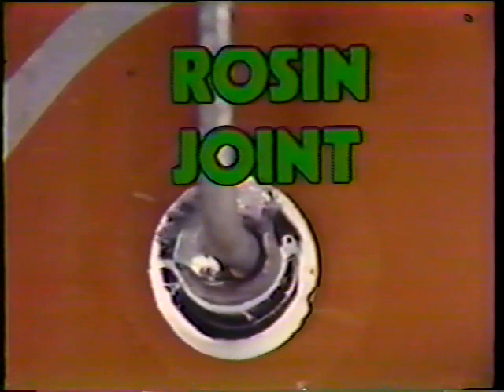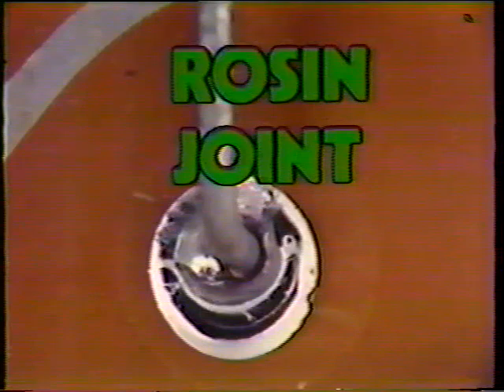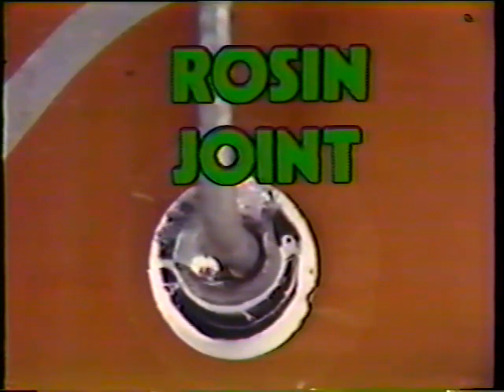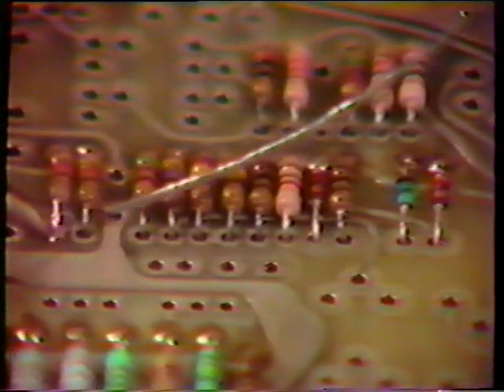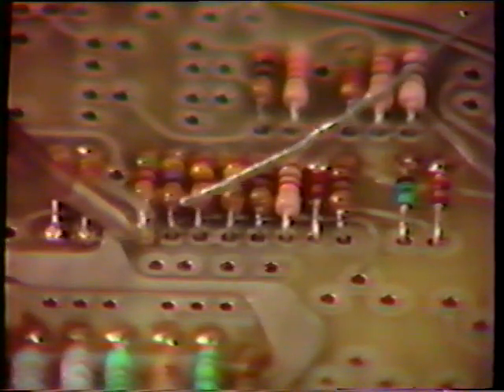This can be eliminated by properly cleaning the joint members and soldering at solder melting temperature. A rosin joint develops when rosin flux gets trapped in the solder. Insufficient soldering temperature and remnants of the cold joint prevent the rosin core flux from escaping as the solder begins to flow. The iron is removed too quickly and a rosin pocket forms. Electrical and mechanical integrity of the joint is seriously impaired—the components or wires are held together only by rosin residues.